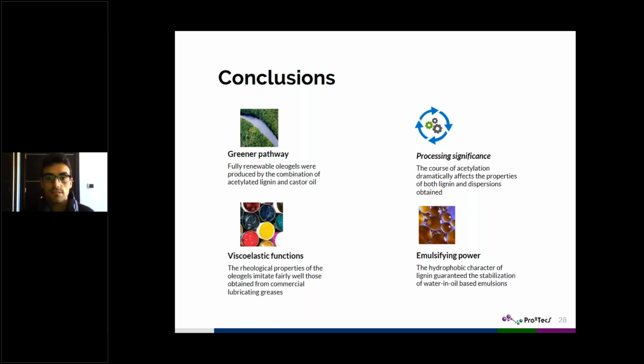Well, again, just to highlight the process's significance, how the course of acetylation dramatically affects the properties of both the lignin and finally also of the dispersion obtained. About the viscoelastic function, just say that the rheological properties of this oleogel imitate fairly well those of the commercial lubricating greases of low NLGI grade. And finally, that this acetylated lignin can play a good role as an emulsifier because of the hydrophobic character that guarantees the stabilization of water in oil-based emulsion.